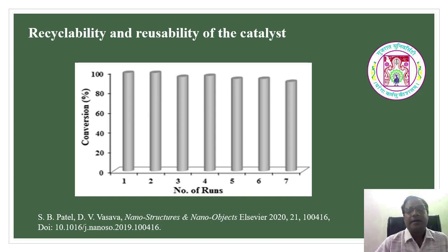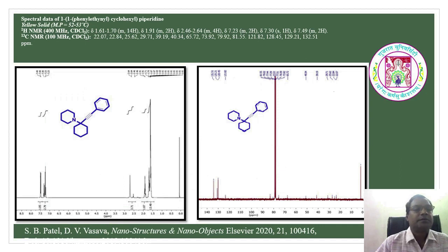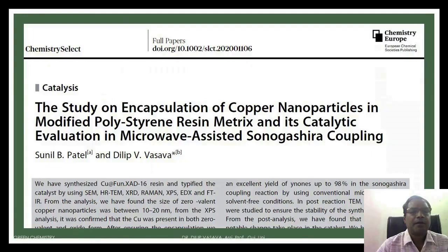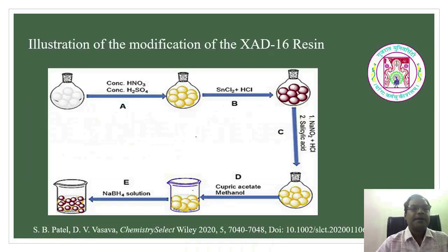solvent free reaction. Also the recyclability of the catalyst is studied, and the activity of the catalyst slightly decreases after the 7th run of the reaction, and the product was also confirmed with the spectral analysis. Very recently, we have also reported another work in ChemistrySelect, that is the Sonogashira coupling reaction, where copper nanoparticles are utilized and support is taken as a polystyrene resin matrix.